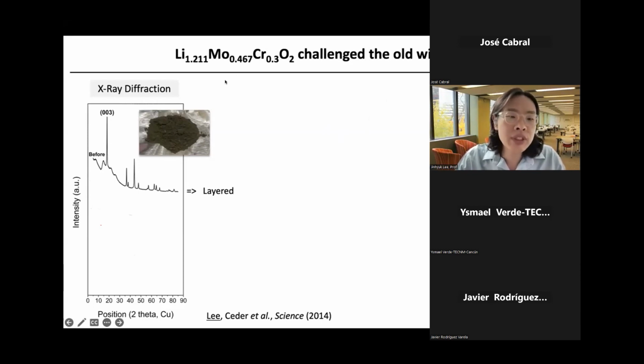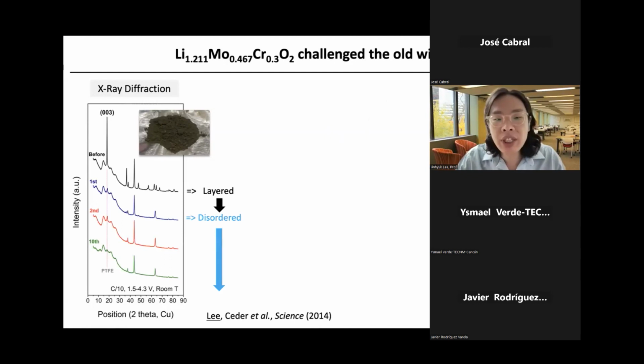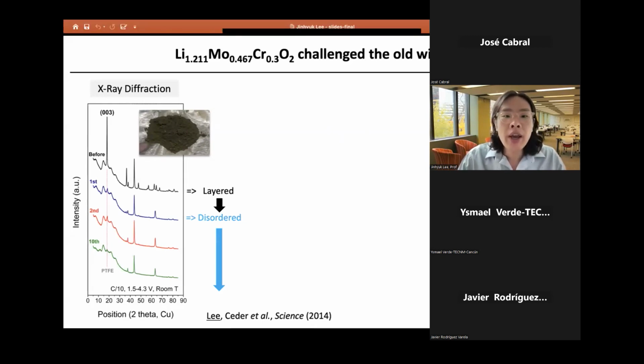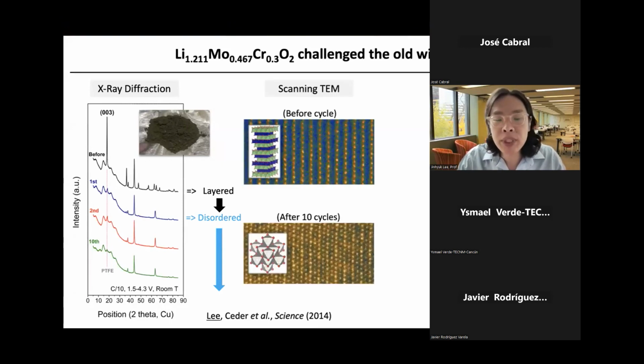This material is very interesting because it initially forms as a layered rocksalt structure, as you can see from this XRD pattern, but it transformed almost completely to the disordered rocksalt structure after a few charging and discharging cycles. This is evidenced by the dramatic change of the XRD pattern from that of the layered to the disordered rocksalt structure. It's also seen from the scanning transmission electron microscopy image that shows the dramatic change from the layered rocksalt contrast, you see the layered contrast here, to the disordered rocksalt contrast. So the conventional wisdom would then expect very poor cycling performance of this material.